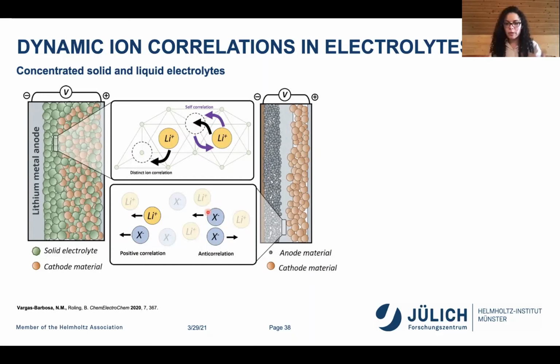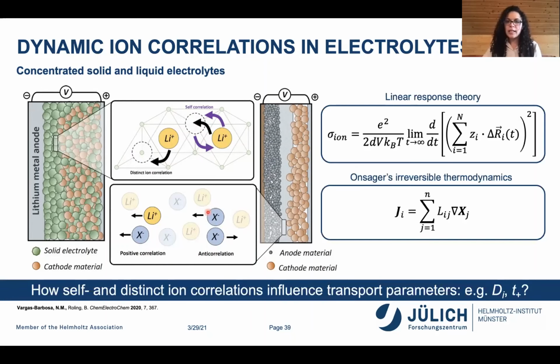Okay, so in this case, we were looking at combining linear response theory with Onsager's irreversible thermodynamics and using these two aspects to determine how these kind of correlations determine tracer diffusion coefficients, self-diffusion coefficients, salt diffusion coefficients, and all of the transfer and transport numbers, transference, that's the word, the transference and transport numbers in liquid electrolytes.